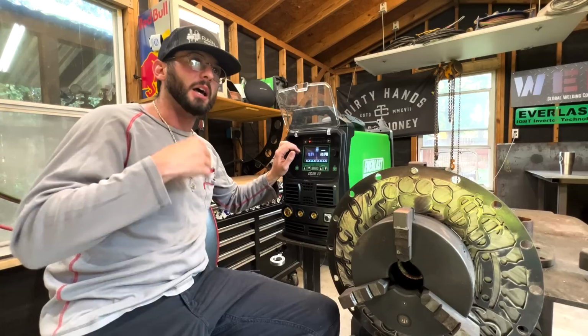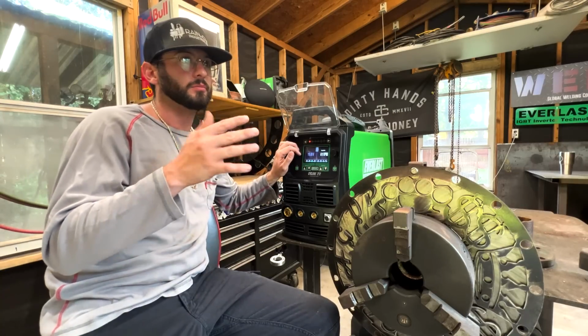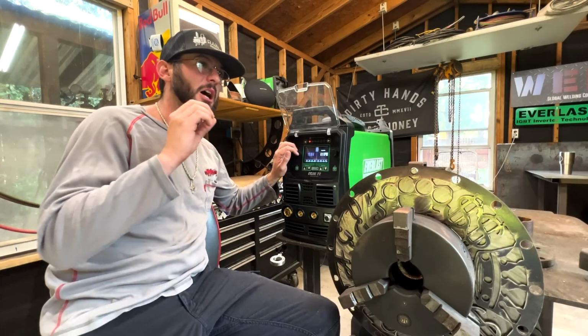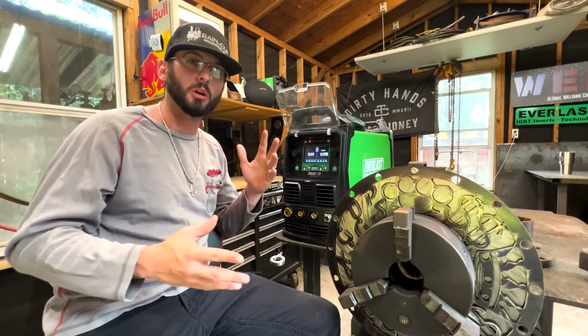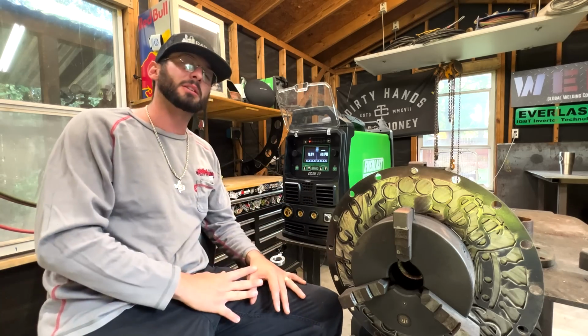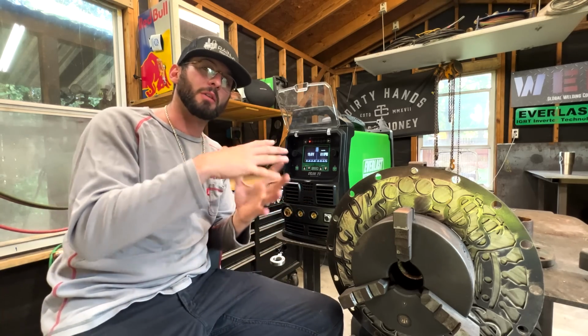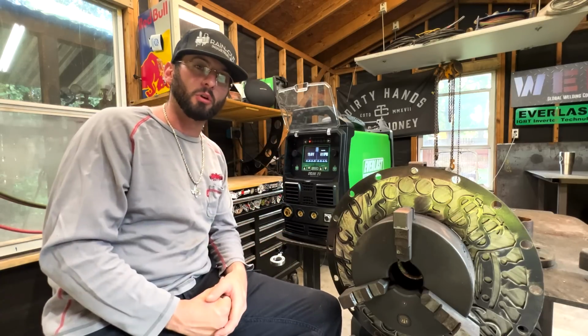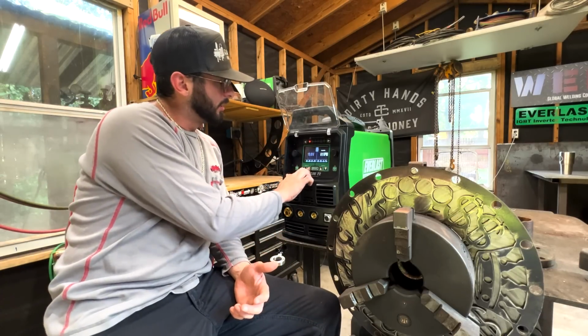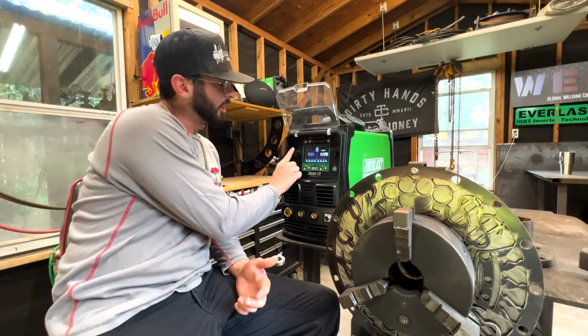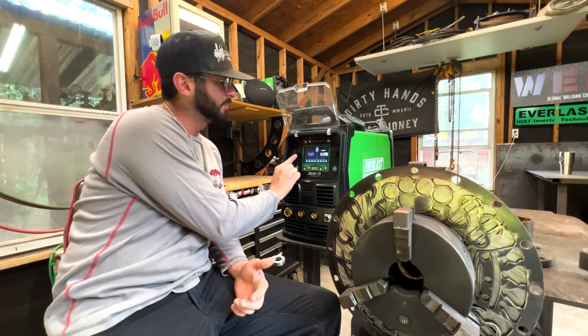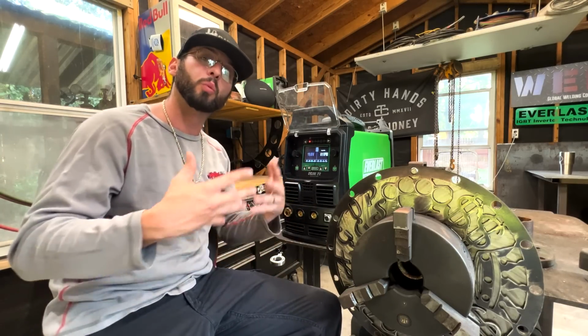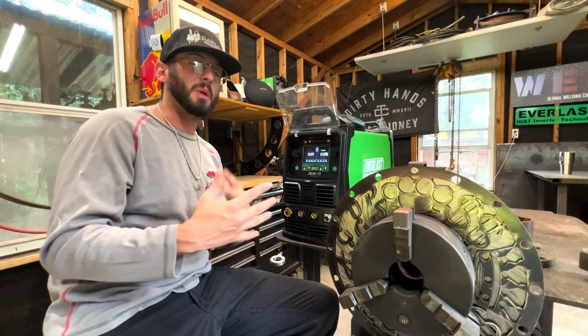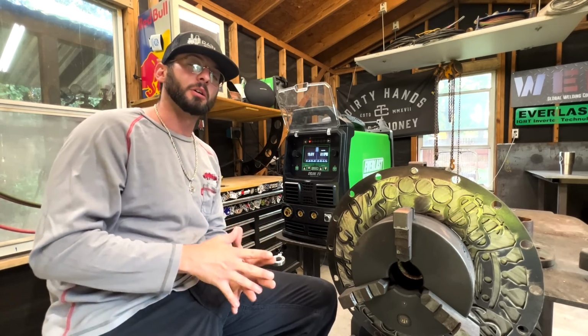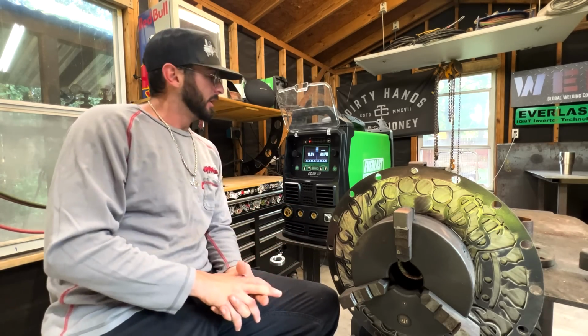So if we go down to the 0% inductance, again, you'll notice a lot crisper of a sound. It's going to have a crunchy, crispy sound and throw off a little bit more hard spatter, things along that nature. You might notice that you have a higher crown in the middle of the weld. Now as we go across the way and we go up to 100% inductance, you might notice a lot softer of a puddle, a lot more fluid, wetter puddle, as well as maybe throwing a little bit less buckshot here and there, so less spatter, if you will.